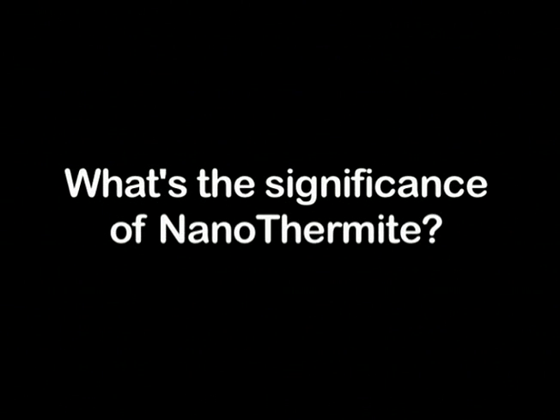What's the significance of nanothermite? The point here is that with the discovery of a high-tech active material, in the words of Dr. Fair, it blows up when you heat it in a differential scanning calorimeter, as you saw from the narrowness of the exotherm. That rate is high. Now, we haven't measured everything we'd like to about it, but those data we have. When we compare with known nanothermite, it's very energetic and very rapid in the reaction.